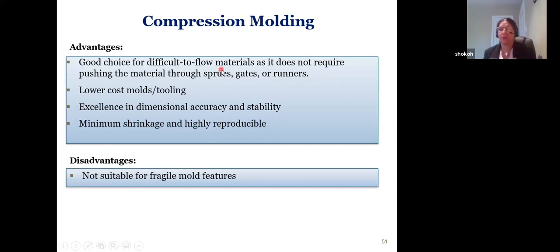The advantage is that you put the uncured composite inside, and you don't need to go through gates, runners or sprue, which is what you mostly do in injection molding. That allows you to use materials that are difficult to flow, meaning they cannot go through the injection port or the runner gates. In compression molding we don't have that problem. The cost of molding and tooling is also cheaper. It is excellent in dimensional accuracy and stability of the final profile, with minimum shrinkage, because shrinkage is not good and we don't want it. And you can make very repeatable, reproducible parts. The disadvantage is you cannot use it for fragile molds.